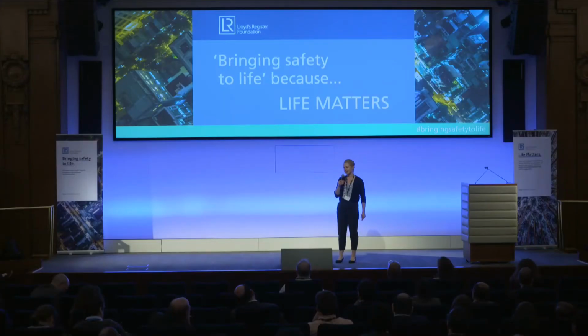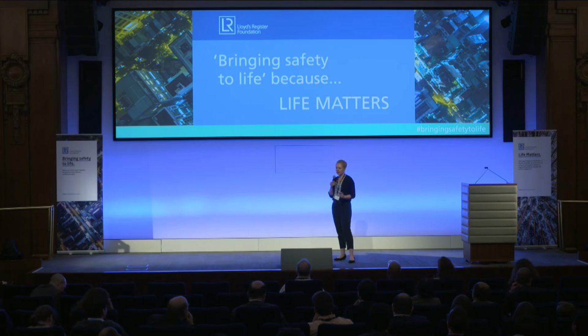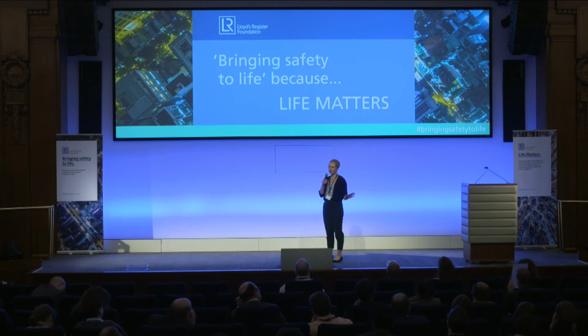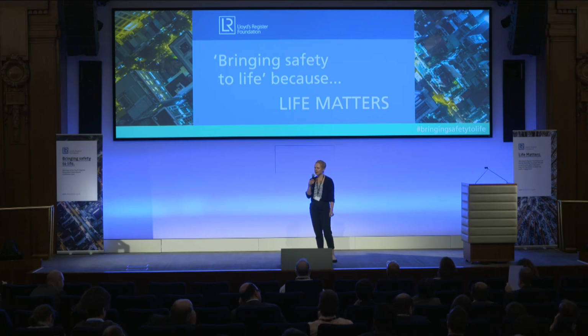Unfortunately, our battery died after already a couple of charge and discharge cycles because the polymer was unstable. Within the last year, I put all my effort into the synthesis of stable and well-performing conductive polymers by studying the interaction of the polymer with the ionic liquid. I'm keen to tell you that we managed to synthesize polymers which were stable over 1,000 charge and discharge cycles, and also showed new insights as battery material.